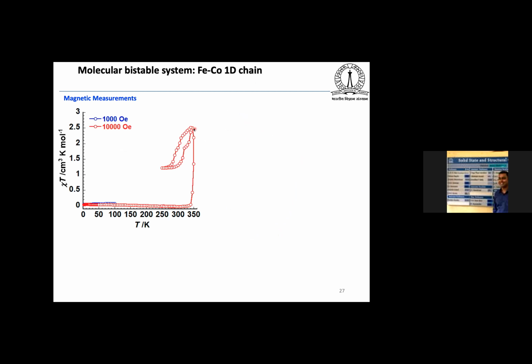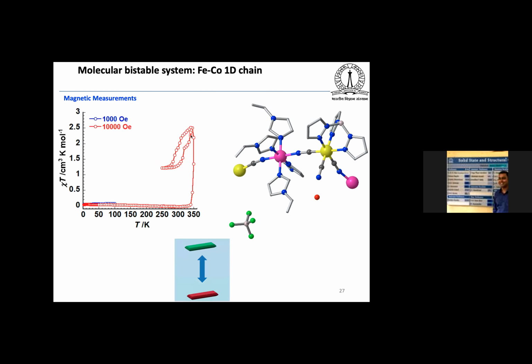And then when you decrease the temperature, it follows another path, and it shows very interesting hysteresis below room temperature. And what we have also observed is that below 300 Kelvin, the system was green in color. But when you increase the temperature to 345, the crystal color changed to almost red, and this is showing a different magnetic property.